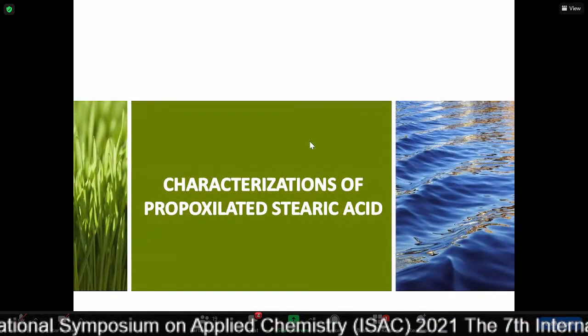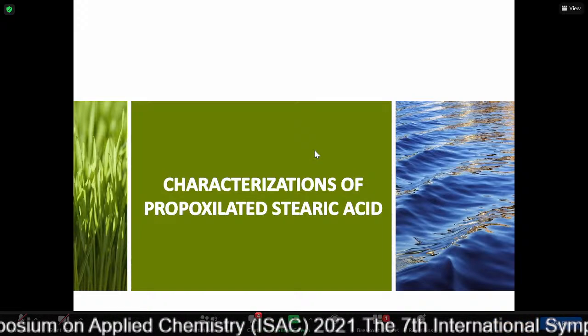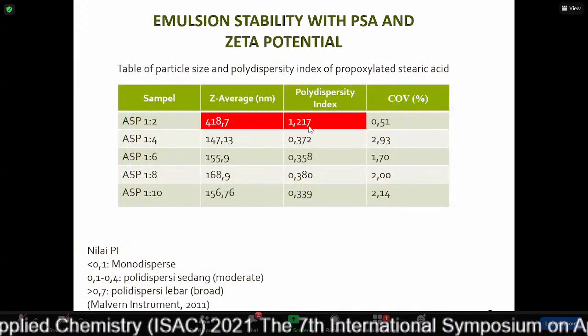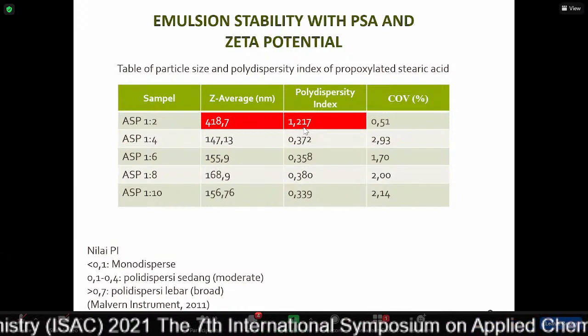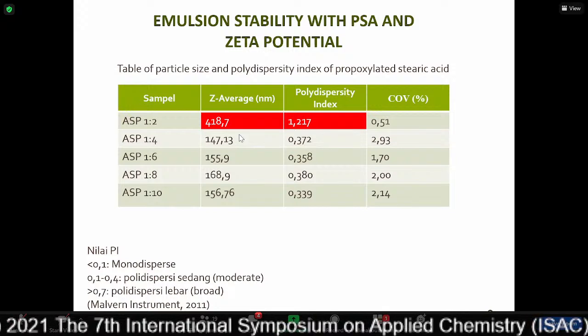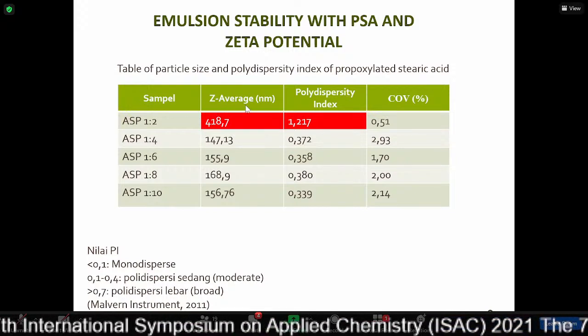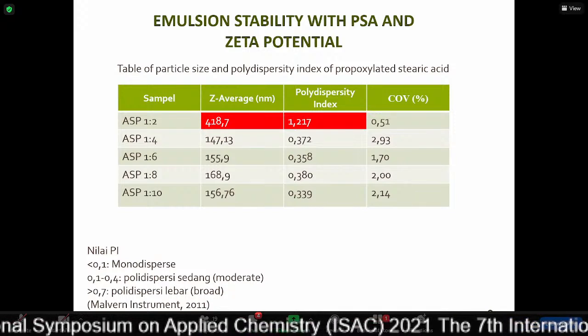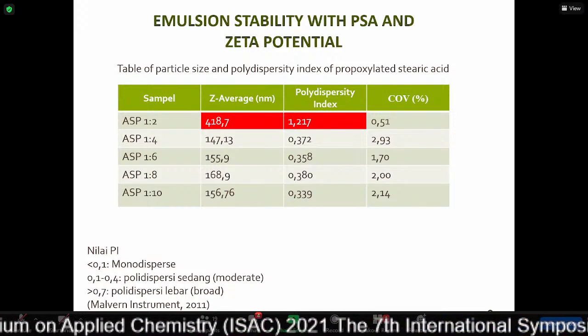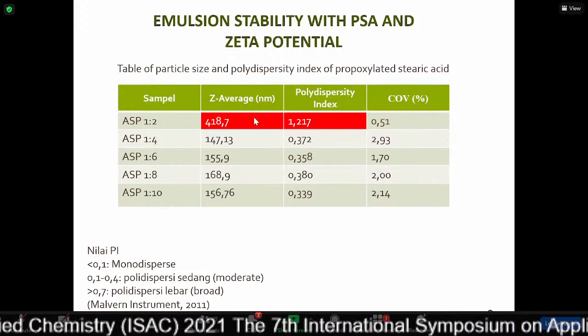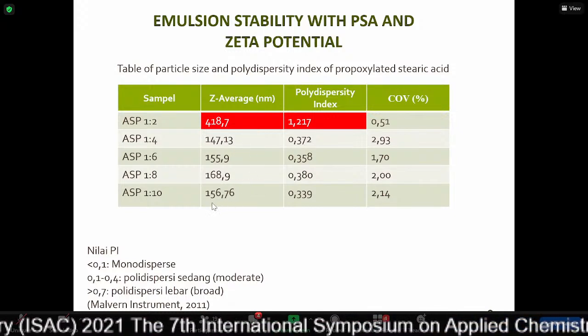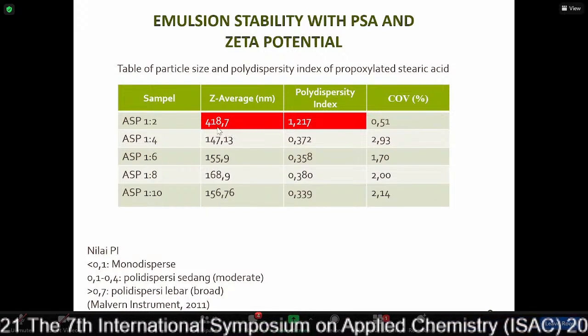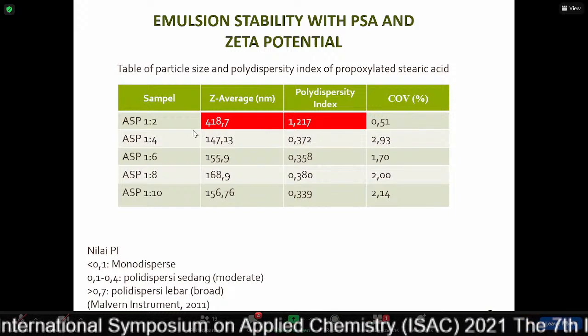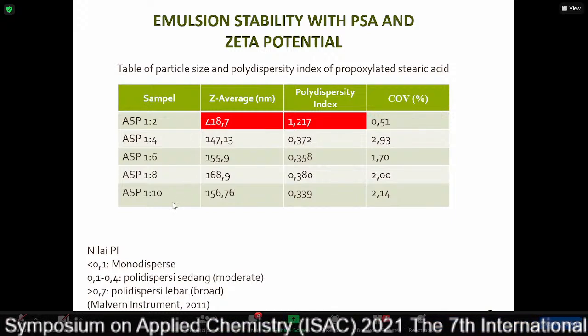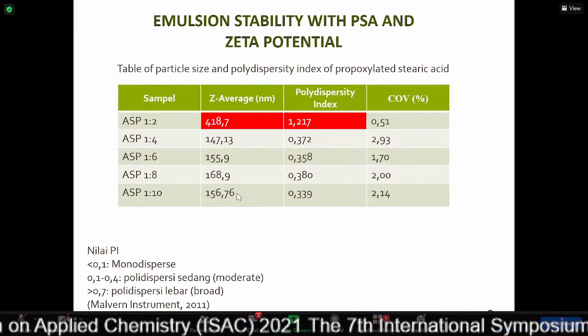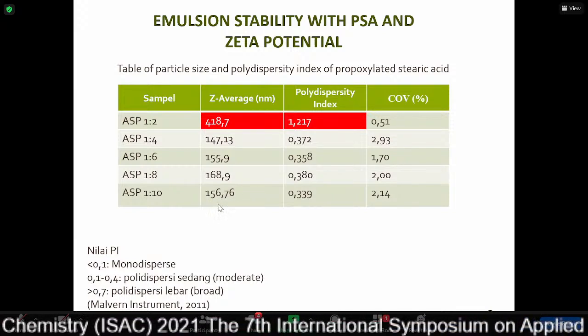This is the physical characterization of the propoxylated stearic acid. This is the particle size and polydispersity index of propoxylated stearic acid. We can see here that the average size of the emulsion droplet in this polymeric surfactant is between 150 nanometers and 450 nanometers. So with a longer chain of propylene oxide, the size of the molecule decreases.